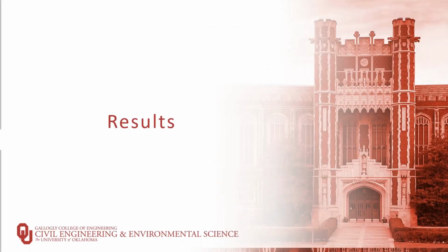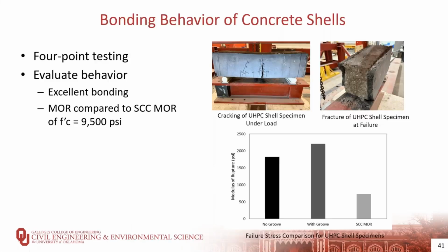And moving on to the results. So in terms of the results, we're going to start discussing the results from the concrete shell trial specimens. 4-point flexure testing was conducted on those 2 specimens to evaluate the flexure strength for the composite element. As can be seen from the picture on the left, a vertical flexure crack occurred at midspan of the specimen, showing a good behavior and bonding between those two different concretes, the UHPC and the SCC.